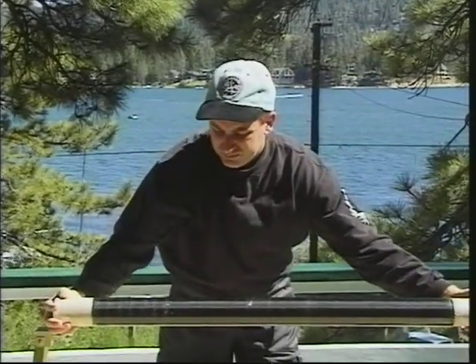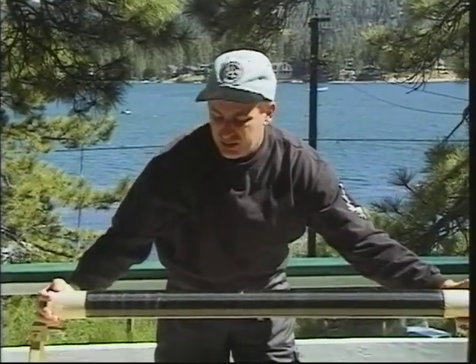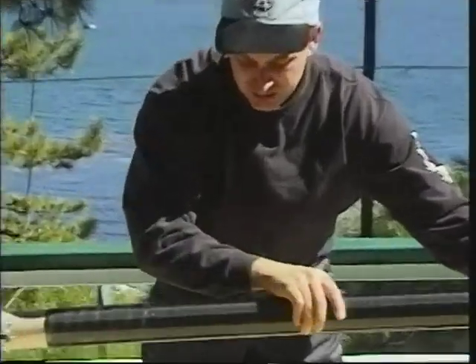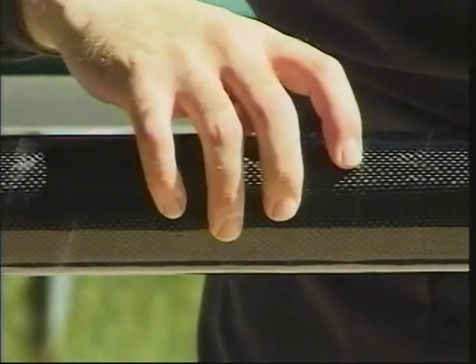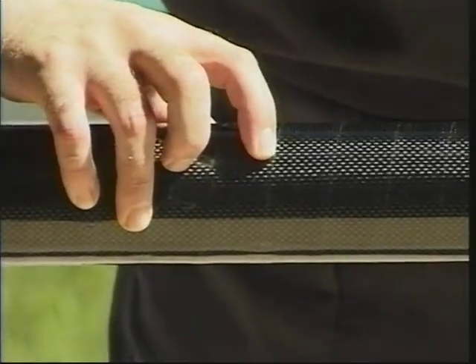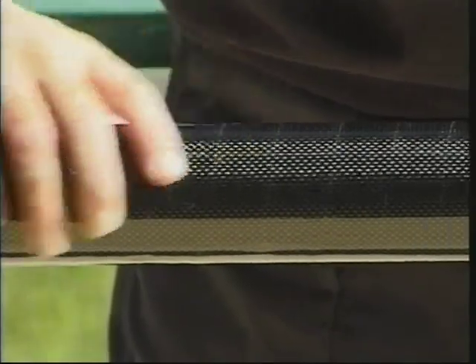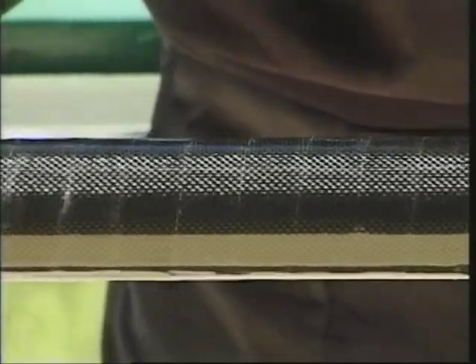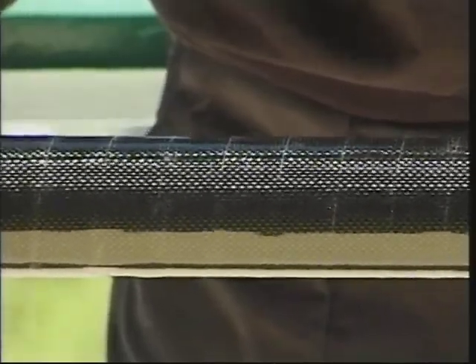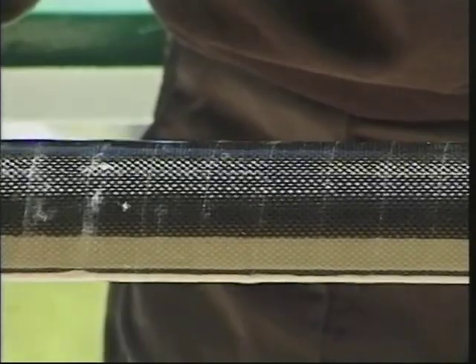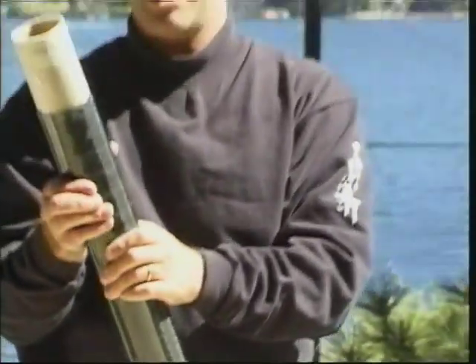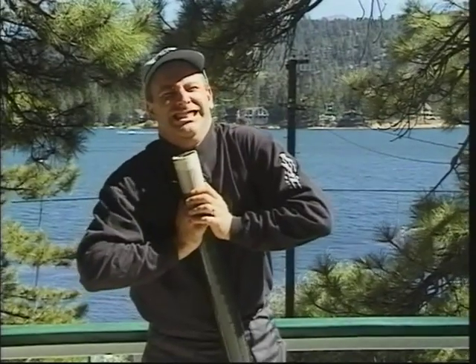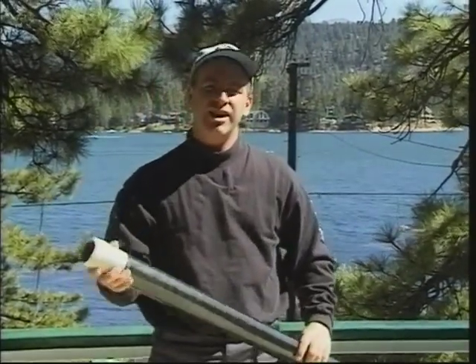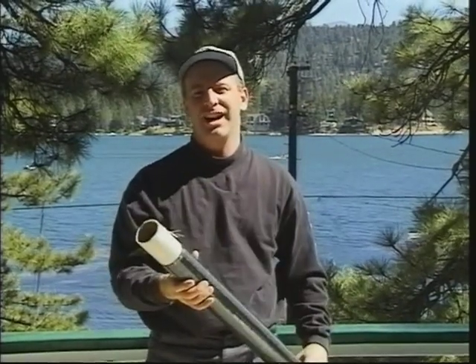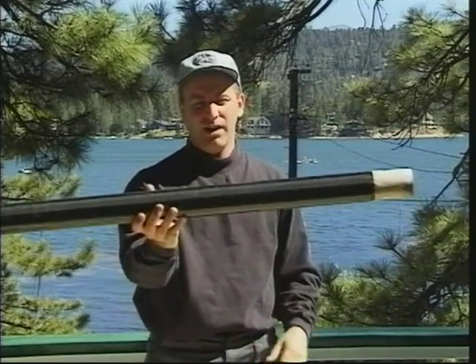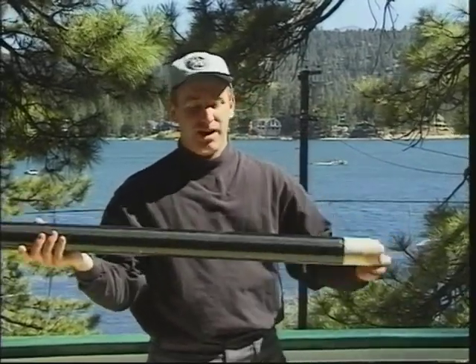What I'm left with is a very, very strong carbon laminate. And we zoom in again to see what we've got. You'll end up with some spiral patterning where the tape overlapped itself. But if you look at that carbon laminate, there's no air bubbles. It's very, very smooth and very, very strong. Two wraps around a standard tube, and I can't compress it at all. This is just a standard paper tube inside that would basically crush in my hands if I hadn't reinforced it. So very, very strong, very, very light. That's carbon fiber.